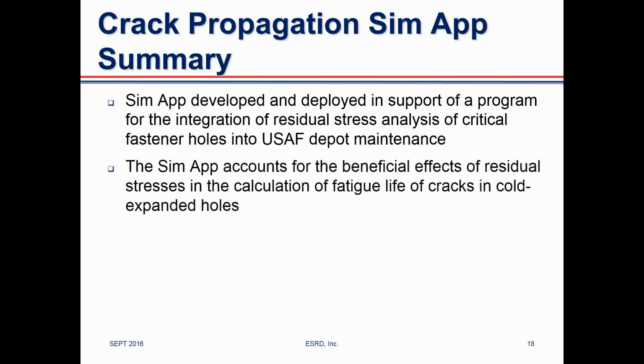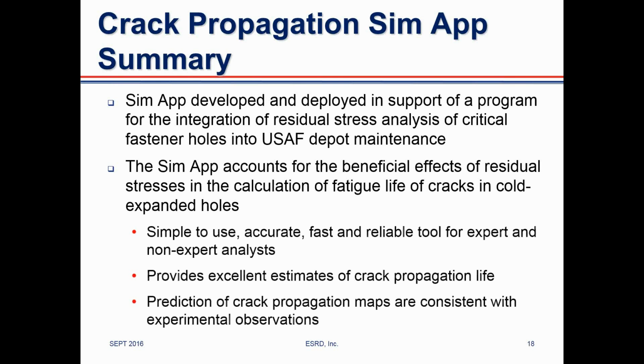The Sim App accounts for the beneficial effects of residual stresses in the calculation of fatigue life of cracks in cold expanded holes. It's a simple to use, accurate, fast, and reliable tool for expert and non-expert analysts. It provides excellent estimates of the crack propagation life, and the predicted crack propagation maps are consistent with experimental observation. Importantly, it also allows very quick assessment of different cold working procedures to get the life that is of interest, in a very simple to use tool.